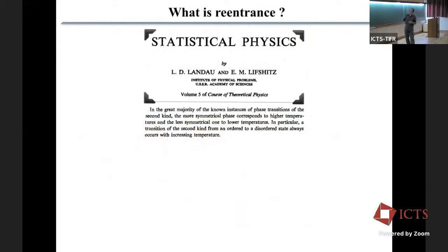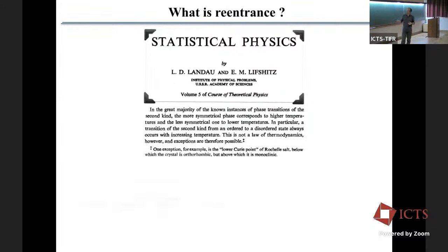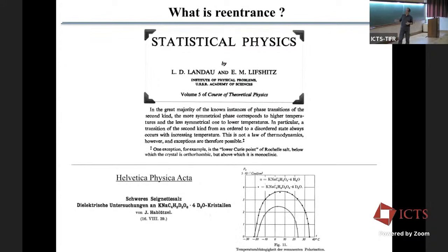But first, what is reentrance? As you know, a very general thing is that when you take a system and cool it down, you go from paramagnet to ordered phase. You always go towards something which is more ordered. But actually, it's not always the case, and you can have exceptions. An example is the Rochelle salt. I found, I think, the first experiment on Rochelle salt that measured this reentrance in Helvetica Physica Acta in 1939. If you measure the electric polarization of this Rochelle salt as you cool down, you have 0 polarization, then you have an onset of polarization, and the polarization disappears. So this is a phenomenon of reentrance: you have a disordered phase, long-range ordered, and disordered phase again.